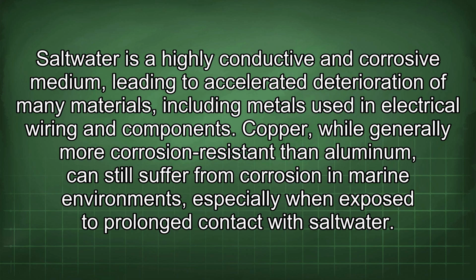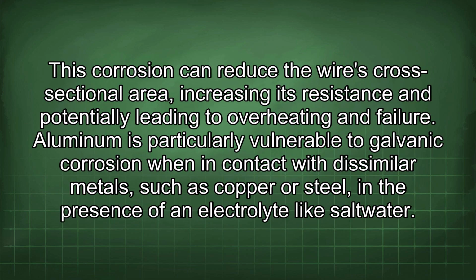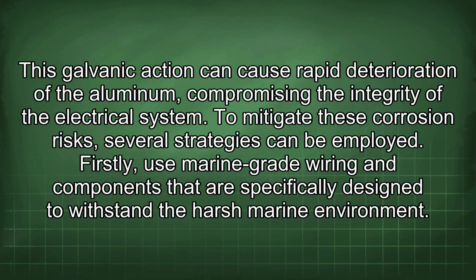Copper, while generally more corrosion resistant than aluminum, can still suffer from corrosion in marine environments, especially when exposed to prolonged contact with saltwater. This corrosion can reduce the wire's cross-sectional area, increasing its resistance and potentially leading to overheating and failure. Aluminum is particularly vulnerable to galvanic corrosion when in contact with dissimilar metals, such as copper or steel, in the presence of an electrolyte like saltwater. This galvanic action can cause rapid deterioration of the aluminum, compromising the integrity of the electrical system.